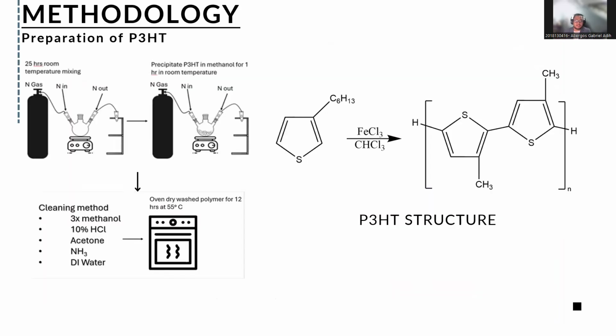So for the methodology, we start with the 25 hours room temperature mixing in an inert environment. Then it will be precipitated in methanol for 1 hour to stabilize the reaction. For the cleaning method, we will have 3 times the methanol, 10% HCl, acetone, ammonia, and DI water, which will then be oven dried for 12 hours at 55 degrees Celsius.